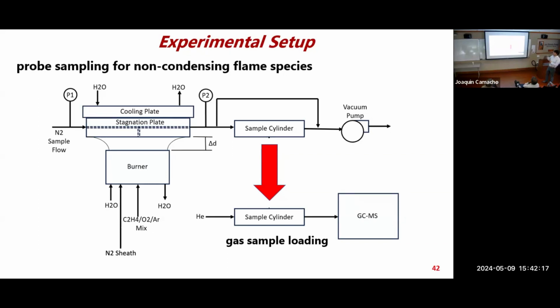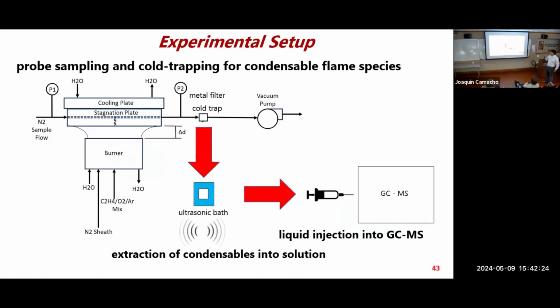So what we did was have two experiments, one for gas phase species, and then a separate one using this condensation behavior to accumulate condensable species over time. Over time is important because these condensable species are gas phase in the flame, but they're also at much lower concentrations, orders of magnitude lower than the CO2, CO, and water. These precursors leading to carbon and soot are orders of magnitude smaller in concentration. So it takes time to accumulate enough.